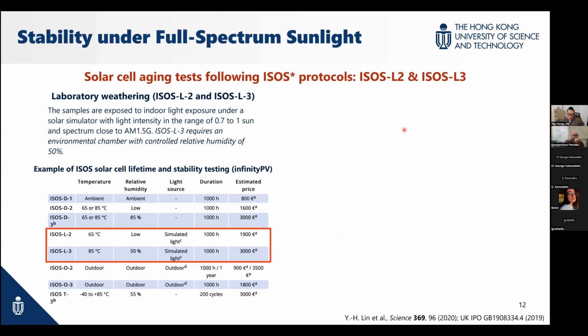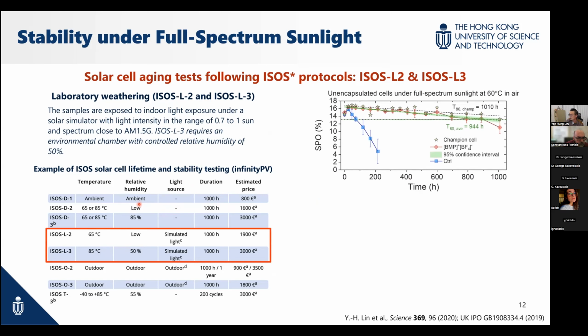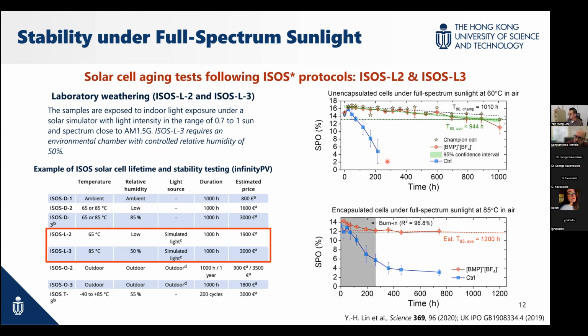All right. So this is what we think happens, from this film characterization using electronic measurement methods. One important thing in perovskite as compared to silicon is to carry out the stability test. The more difficult one is to combine light and heat. What we found from our results is that we have improved the stability a lot by using this additive. As compared to the reference, it has roughly 3 to 4 times enhancement.